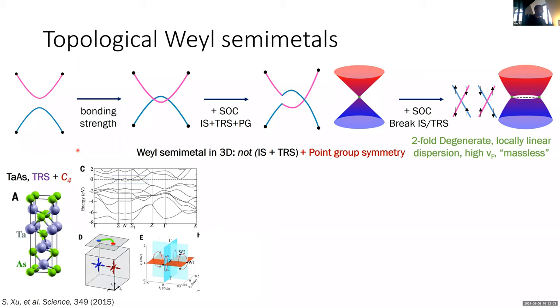in inversion symmetry breaking. So you can see, because of this pair of atoms here with the single atom here and the pair rotated by 90 degrees, there is not actually an inversion center in this unit cell, right? And if you fold those through the inversion, they would basically be where these purple or blue atoms would be, not over here. So this compound, sure enough, did exhibit Weyl points and has manifested a few interesting properties over the years, including these high mobilities and interesting orbits related to the Weyl points.